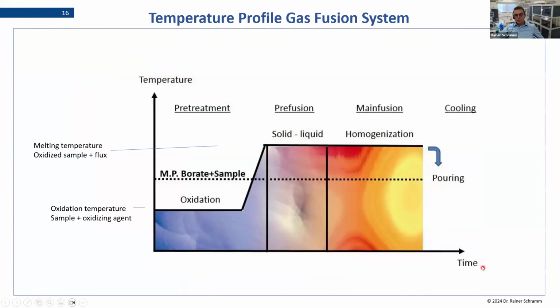If we look at a gas system, it's completely different because the system works from cold to cold. And the cold sample is sitting in the beginning in the machine. And then you heat and you increase the temperature. So this is then the ramp where the temperature is going up. The heat is introduced into the material, and then it will go from solid to liquid. And when it's liquid, we start there the homogenization.